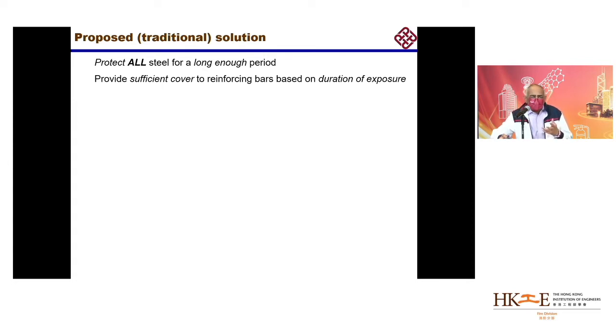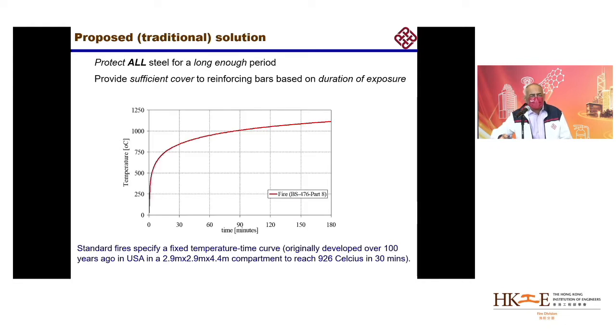Based on that understanding, the traditional proposed solution is to protect all steel for a long enough period because of its properties, but provide sufficient cover to reinforcing bars, because concrete is typically not just concrete; you have steel inside it, reinforcing bars. So we provide cover to reinforcing bars for a sufficient depth, so that they are protected from the heat effects.